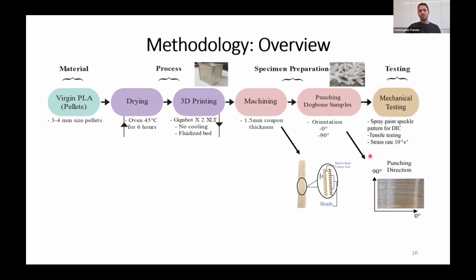And as I've mentioned, we had 2 orientations. 0 is along the bead, 90 degrees is 90 degrees from the bead. And then the further step is the mechanical testing that we did. But what I have explained is one pass of the polymer process. And I said that we wanted to do multiple passes.